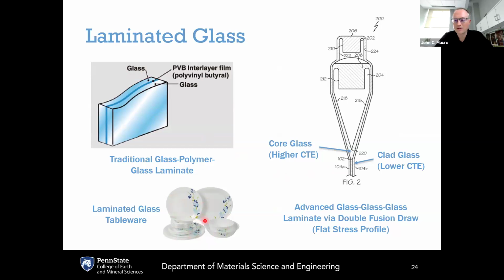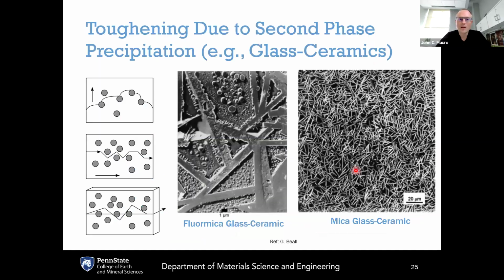And what gives these dishes their strength is the difference in the thermal expansion coefficient between the outer layer and the inner layer. This can also be done in flat glass forms. And in fact, one of the projects I worked on for a number of years at Corning was this double fusion draw process, where you've got one glass that's being melted up above, another glass down below. The upper glass flows over the inner glass, and what you get is a 3-layer laminate at the bottom that automatically gives you strengthening based on the differential in the CTEs between the clad glass and the core glass.